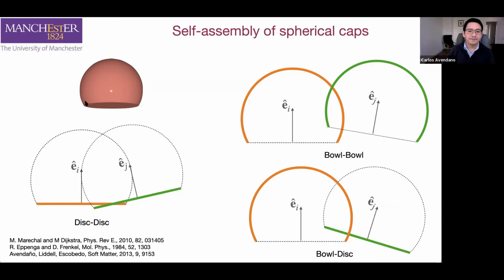We decided to decompose this particle into 2 objects. We can model this non-spherical particle as being formed by a spherical shell, which I'm representing here, and is capped by a flat disk at the bottom. So essentially with 2 objects, we can model the particle that we want.